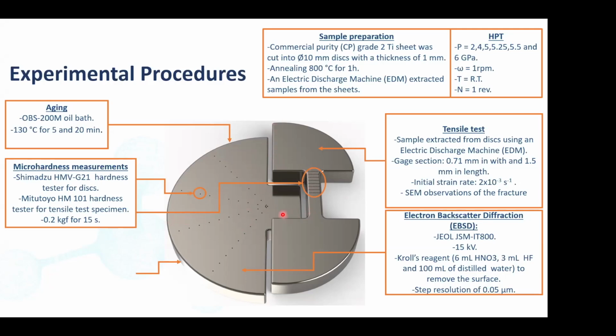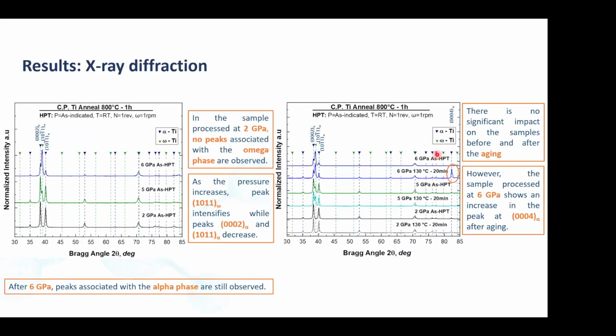We can also remove by EDM, electrical discharge machining, for example, small size dog bone specimens for tensile testing. And then, of course, we can carry out microstructural observations by TEM, EBSD, or others. So just very briefly, we did some interesting work changing the pressure in the commercial purity titanium. Especially, we knew that changing the pressure, for example, from 2 to 6 will change the fraction of the omega phase. But if we really want to narrow down and tailor how much of the omega phase is formed and how it is formed, we wanted to change the pressure very systematically and as finely as we could.